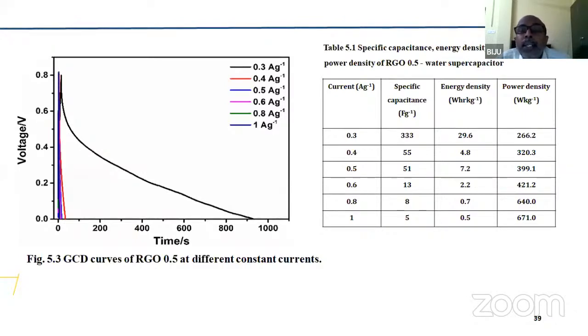And in order to obtain the specific capacitance, the charge-discharge experiment was done. You can see that at 0.3 ampere per gram, the charge storage is there and the discharge curve is also there, from which we could obtain the specific capacitance. The specific capacitance at 0.3 ampere per gram is very high, actually. It is 333 farad per gram. And even at 1 ampere per gram, you have some capacitance, like 5 farad per gram.